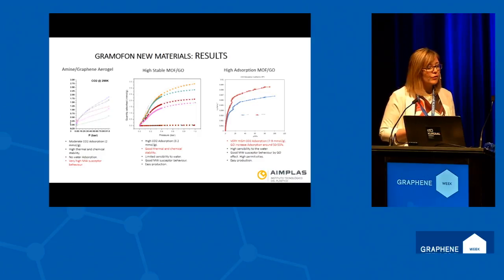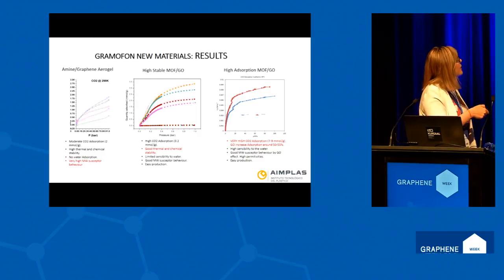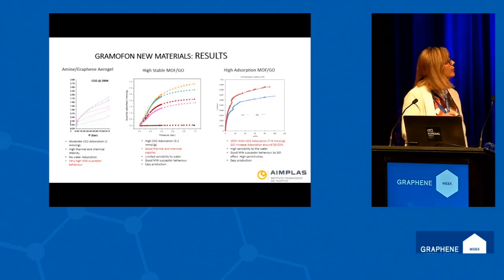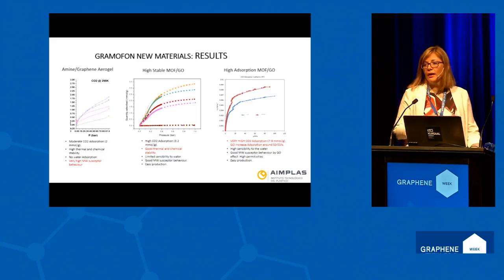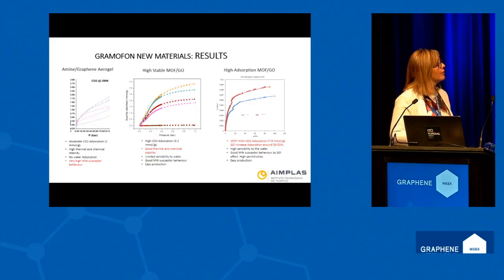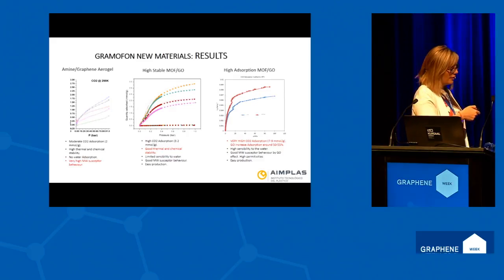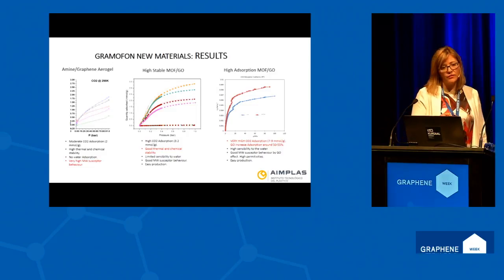And these are the results of the project. Here we have used different metal organic frameworks, and we have obtained, well, very high absorption capacities in this case, but this has a disadvantage about the water sensitivity. So we can use this type of sorbents if we remove the water from the system beforehand, or we can use that combination where we have a good CO2 absorption, but less sensitivity to water.